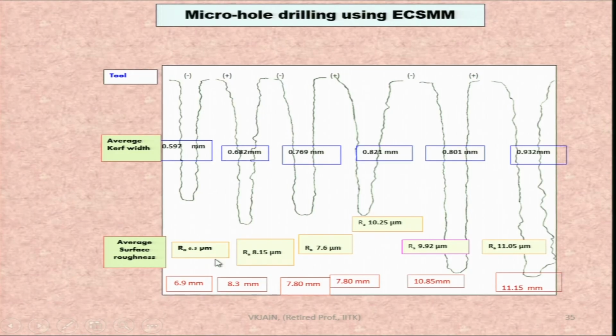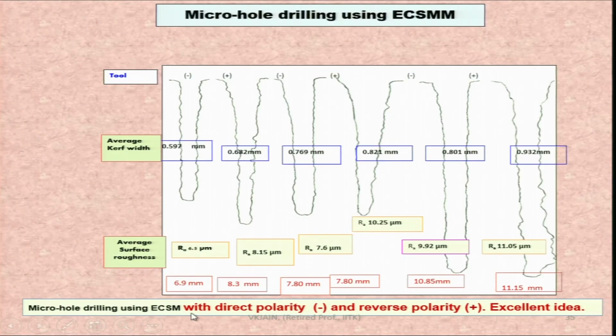And the surface finish that is observed, the average surface roughness value is 6.5 micron, 8.15 micron, 7.6 micron, 10.25 and so on. So, one can see that the surface finish is also very poor after electrochemical spark micromachining. So, it requires proper finishing before really using such cavities. So, micro hole drilling using ECSM with direct polarity and reverse polarity. The minus indicates the direct polarity and the plus indicates the reverse polarity. We will discuss details of direct polarity and reverse polarity in the next lecture, and Mr. Adhikari has done a lot of work on this interesting aspect of electrochemical spark micromachining.